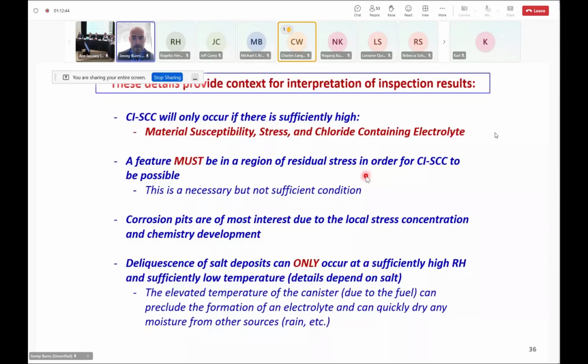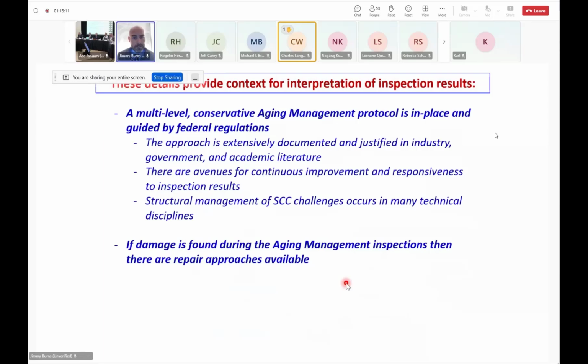The deliquescence of salt deposits can only happen at sufficiently high relative humidities and sufficiently low temperatures, just thermodynamically. So the elevated temperature on the canister can preclude electrolyte formation. And if things do get wet, as Jerry showed for the blowing rain ingress, that moisture would quickly dry on the surface. And lastly, there is a multi-level and conservative aging management protocol in place, guided by the federal guidelines.